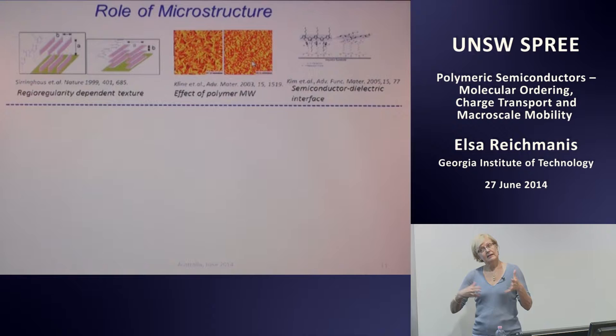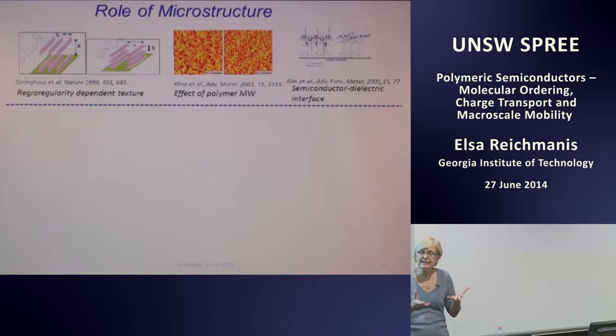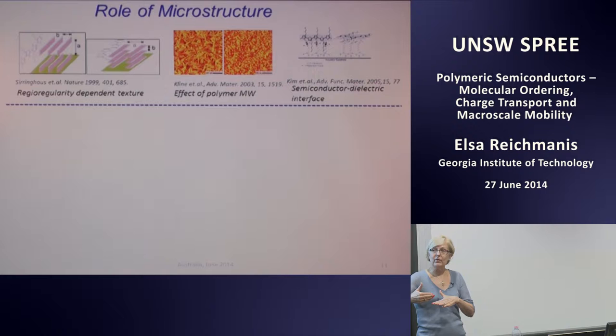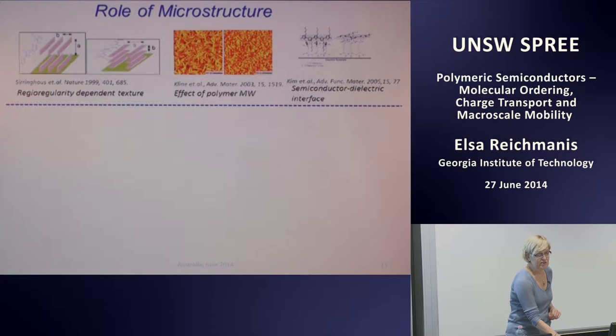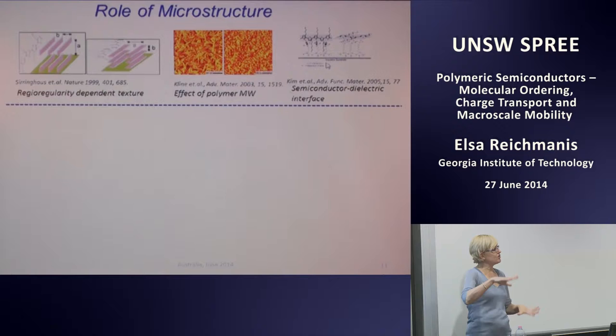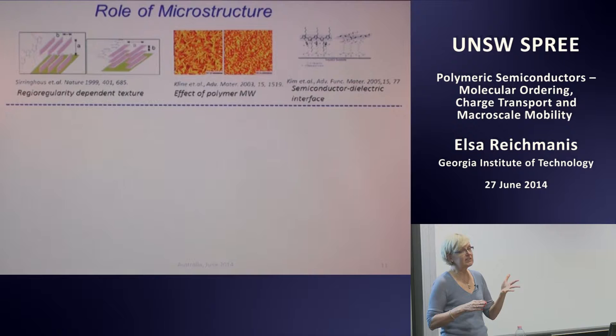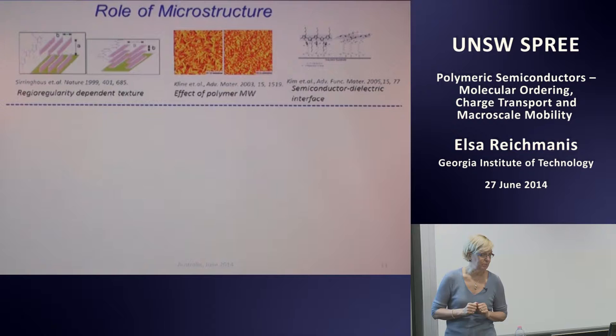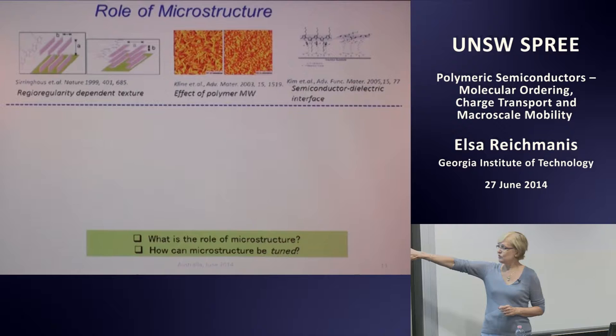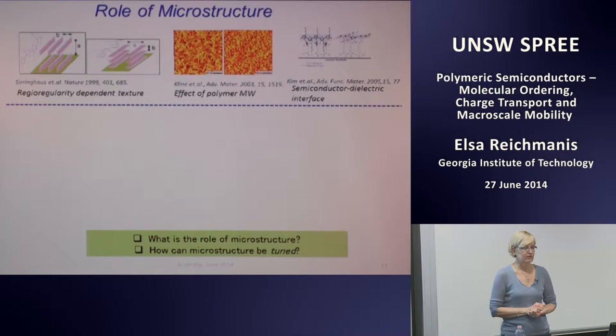And part of the reason for that was speculated to be increases in the number of grain boundaries in the lower molecular weight, more crystalline material. And then it's also possible to modify the surface, change the polarity of the dielectric, rather, and that can impact how the semiconductor will interact with the surface and what its orientation on the surface will be. All right, so what is the actual role of the microstructure in defining charge transport characteristics, and how can it be tuned?